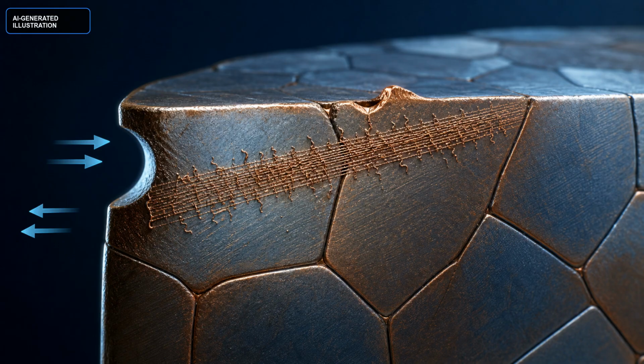Inside that tiny region, metal is not a featureless block. It is a collection of grains and defects. Repeated shear makes dislocations move, pile up, and rearrange. Favorably oriented grains form persistent slip bands, narrow planes where the forward and reverse motion is not perfectly reversible. Surface intrusions and extrusions grow. A crack can start along one of these bands even while the part still looks smooth and still passes an ordinary static check. Sandia's review of high and very high cycle fatigue describes cracks forming at cyclic levels significantly below macroscopic yield, with lives extending beyond 1 million cycles.